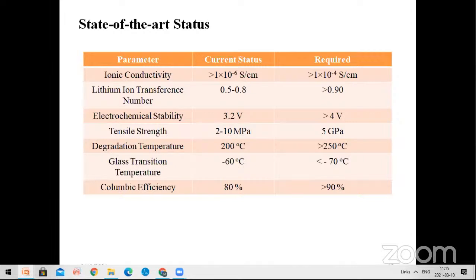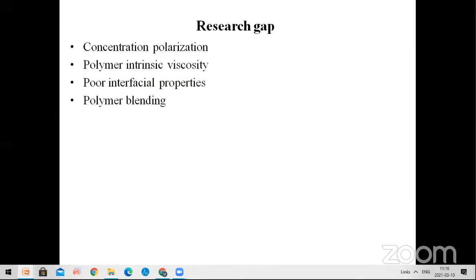What are the parameter requirements for the polymer electrolytes? The first one is ionic conductivity. In the current status, some polymers show 10 to the power of minus 6, but the requirement is 10 to the power of minus 2 to 10 to the power of minus 4. Then lithium ion transference number, which is around 0.99, and the electrochemical stability window, tensile strength, glass transition temperature, and Coulombic efficiency. Because of this, there are some research gaps: concentration polarization issues, polymer intrinsic viscosity, poor interfacial properties, and polymer blends.